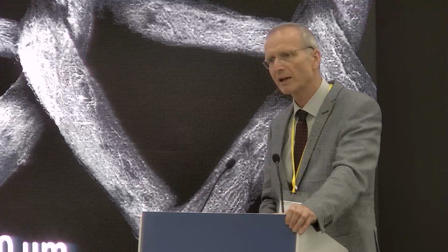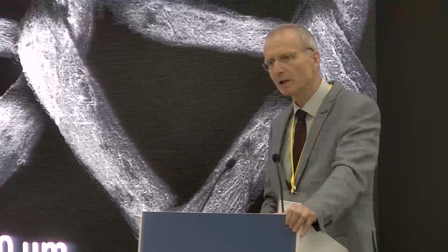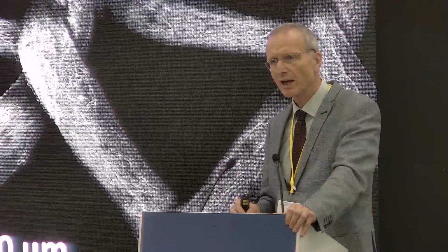On the other hand, I would like to underline that this material has a great disadvantage, because nanofibers have very weak mechanical properties, and that is why you are able to damage them very easily on the surface of the yarn. So only if we are able to gently entangle these yarns, when one yarn protects another one, is the material more or less mechanically resistant.